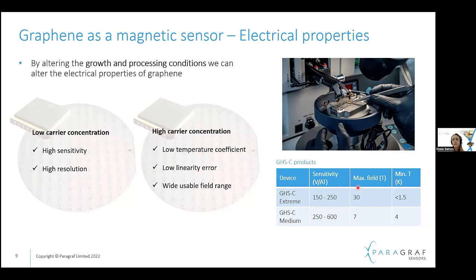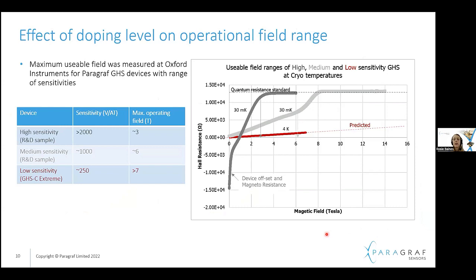This is something I've just highlighted here with our cryo-rated products. You can see they have different sensitivities based on this control of carrier concentration, and then different field and temperature ratings depending on the application. To demonstrate why we need to control these things at cryogenic temperatures, this is data using 3 different sensitivities. We've called them high, medium, and low sensitivity devices. However, you can see that the sensitivity of the low sensitivity device is still 250 volts per amp Tesla, which relative to these ones is low, but actually that's quite sensitive.